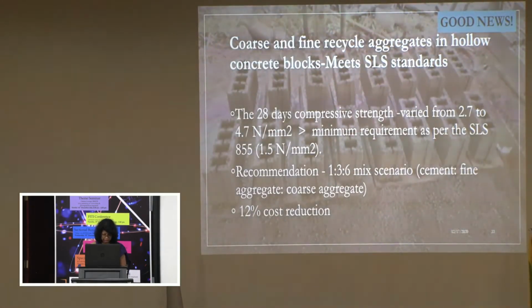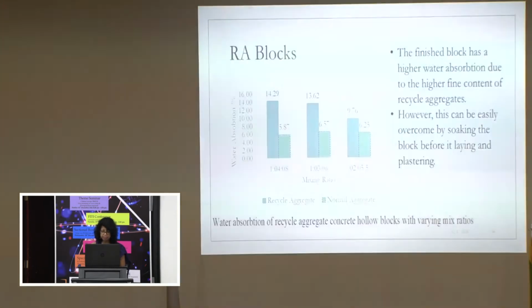The 28-day compressive strength of all the types of recycled aggregate hollow blocks was able to meet the minimum requirement as per the SLS 855 standard of 1.5 newtons per millimeter square. It was seen that a mixture of 1:3:6 was the most economical among the studied mixtures. And recycled concrete hollow blocks have the potential to give a cost-effective, sustainable solution to manage the increasing volumes of demolished waste as well.